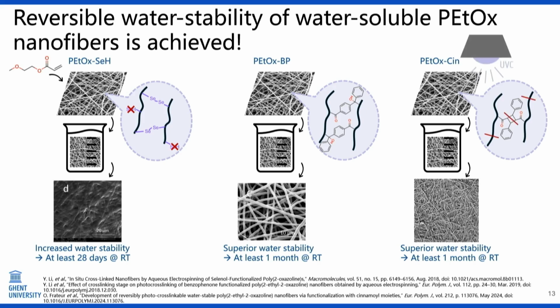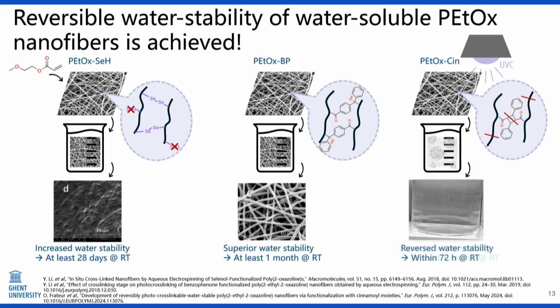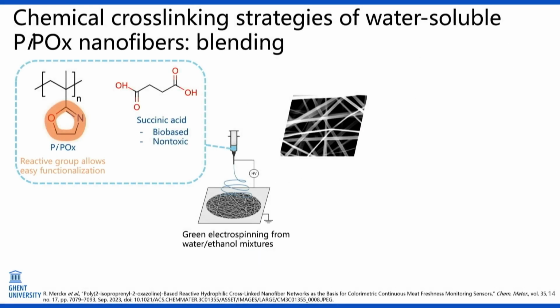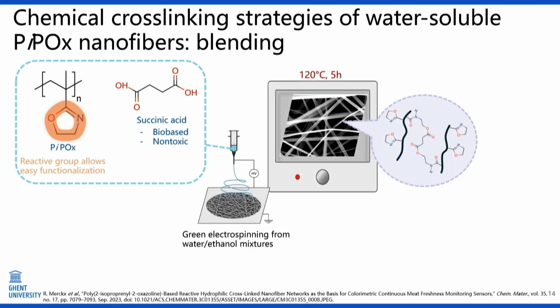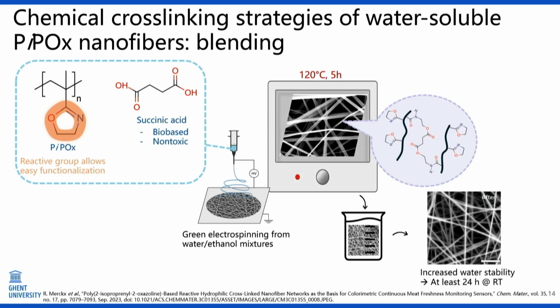The interesting part on the latest member, cinnamoyl here, is that by a UVC treatment, we can reverse the water stability and make them water soluble again, allowing for an easy removal after use if that could be interesting for many applications. Also, the PiPOx polymer can be cross-linked chemically, but through an even easier strategy. We don't need a copolymer here. We can just co-electrospin it with succinic acid and then give it a thermal treatment, which will already induce our aimed water stability.